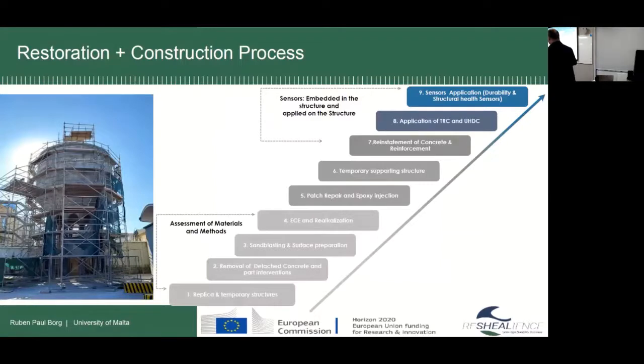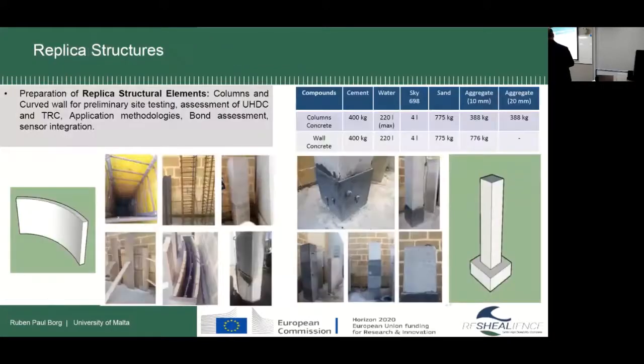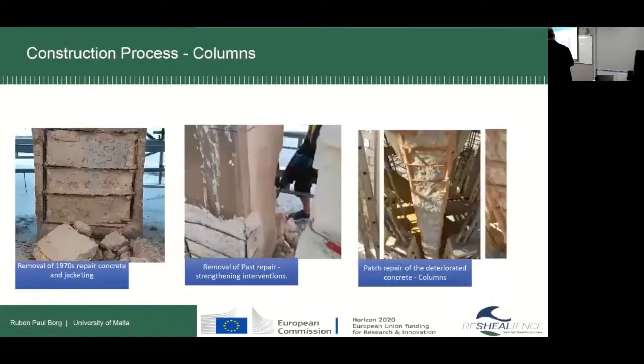So the lab work, then the site work started: removal of all the parts, preparing the surface. In the case of reinforcement, there was replacement of the damaged one, but also realkalinization of the surrounding concrete. It was damaged by carbonation and chloride corrosion, patch repair, build the temporary supporting structure, and go up to the completion of the work. So you see, these are the replica structures of the curved wall and of the columns, which were built and tested in the lab, different tests which were done.